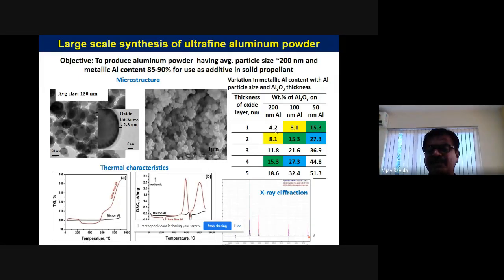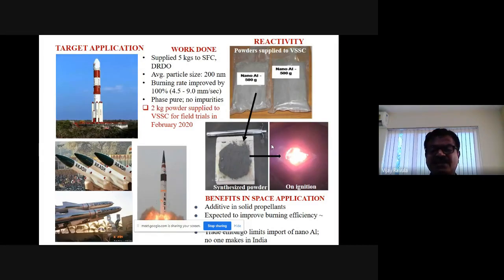So that's why they put it around 200 nanometers in size, and then maintained around 2 to 3 nanometers. So it's around 8% oxide, but still 85 to 90% is metallic content. So that's why they have worked with different techniques and done that. So this is what I was trying to use.